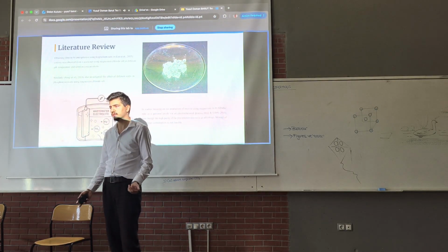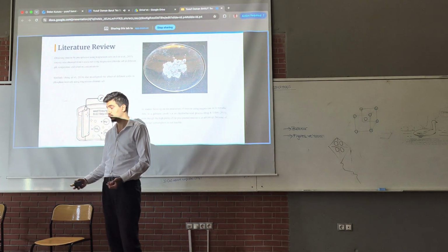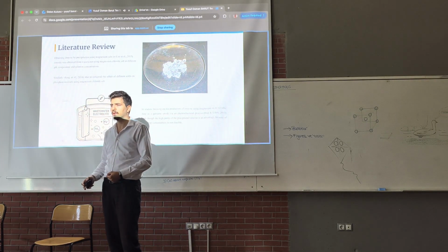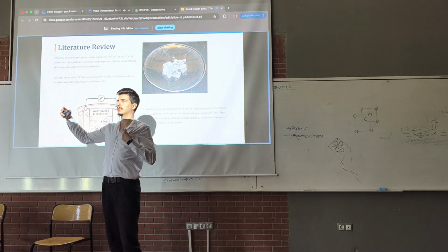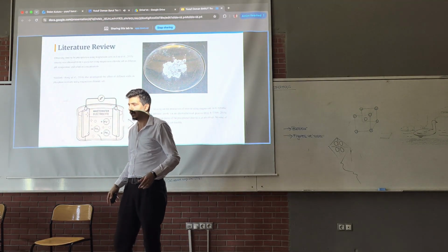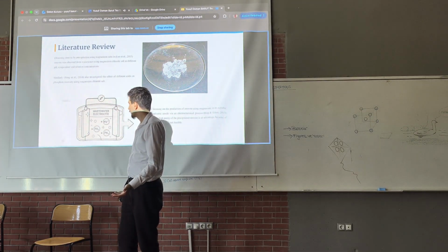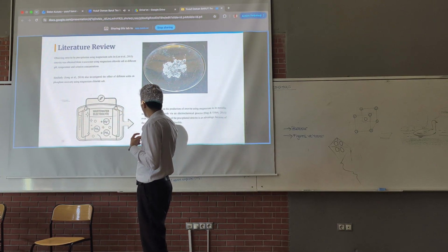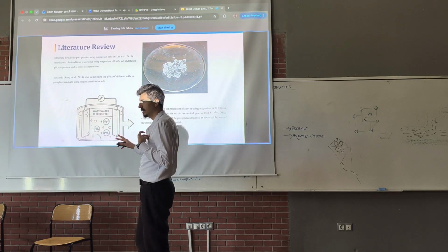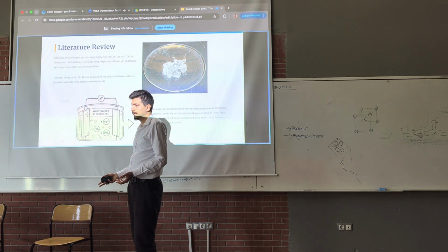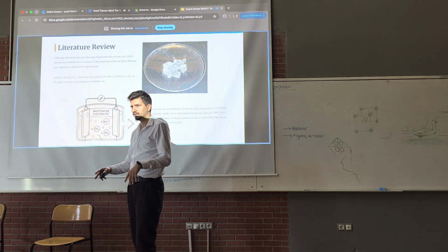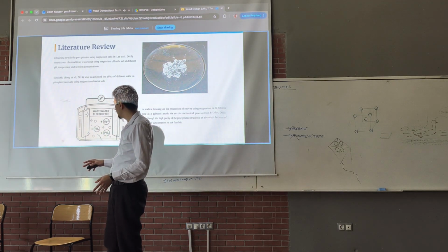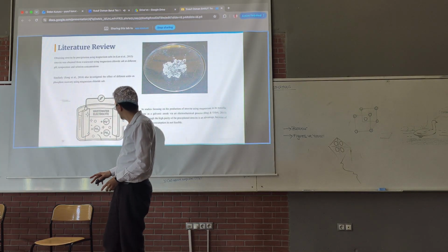Our preliminary studies show us that struvite can be acquired by dipping the magnesium alloy plates into ammonium dihydrogen phosphate solution. And mainly they are using magnesium salts, and they precipitate the struvite inside these systems.